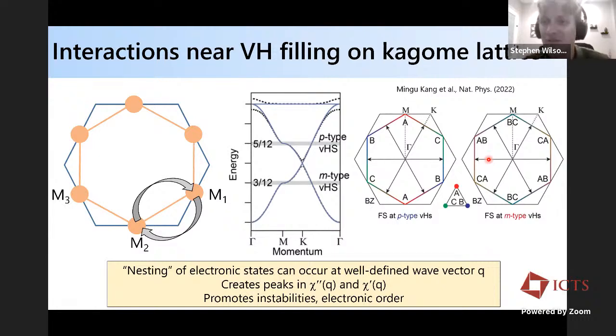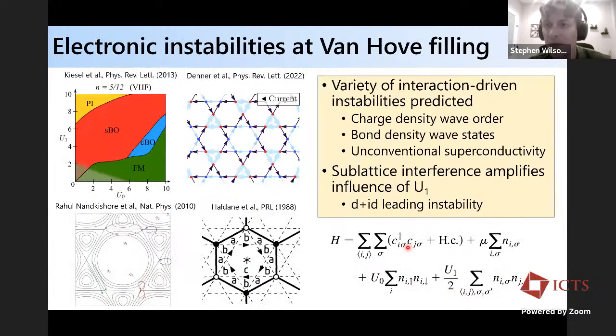And so, from a correlation physics standpoint, one wants to try and explore whether or not you can have nesting between these M-point Van Hove singularities, where you should create peaks in the electronic susceptibility and potentially unconventional forms of electronic order. And indeed, looking at the Kagome lattice Hubbard model, there are a lot of interesting phases that are predicted if you can tune the Fermi level near these Van Hove singularities. So, for instance, different flavors of charge density wave order or charge bond order, as well as unconventional superconductivity are predicted to appear.